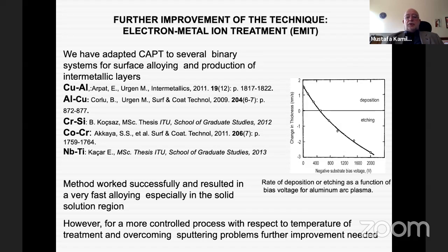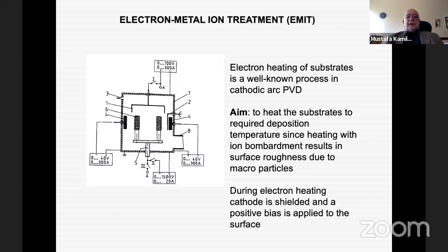However, we want a more controlled process with respect to the temperature of treatment, because you apply a very high bias voltage during your modification, and you somehow also sputter away some of the species that are formed on the surface. So we thought, can we further improve this method? And when you look in the literature, as I said, the cathodic arc plasma contains lots of electrons. Normally, these electrons, under operating conditions, go to the walls of the chamber, which is grounded. So they are useless. They only heat all the walls of the vacuum chamber.